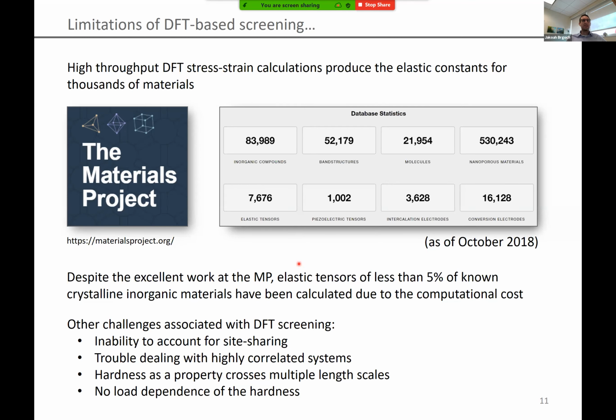Even then, this is still only a fraction of the number of elastic tensors that have been calculated. In order to calculate the elastic tensors, you have to use density functional perturbation theory, and this is computationally a pretty big task. So doing high throughput calculations, although possible, is expensive. And even then, if we start thinking about the number of compounds that have been calculated, this is still less than 5% of the known inorganic crystal structure databases.